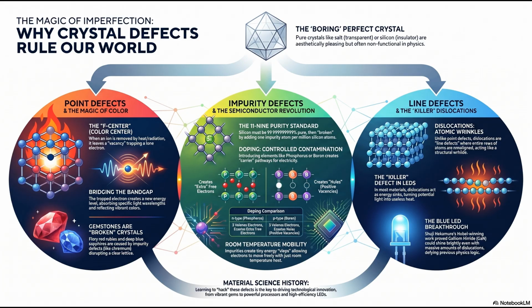Indium. Okay, what does indium do? When you mix indium into the lattice, the indium atoms, which are slightly larger, don't distribute perfectly evenly. They tend to cluster together in microscopic patches due to internal strain. So we have clusters of impurity atoms scattered throughout the shredded lattice. Yes, and these specific clusters of indium cause localized dips in the band gap energy. They create tiny, microscopic, three-dimensional valleys of low energy. The literature refers to these as compositional fluctuations, or more simply, quantum wells.